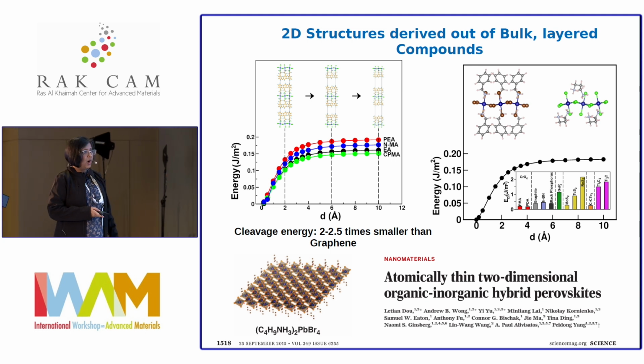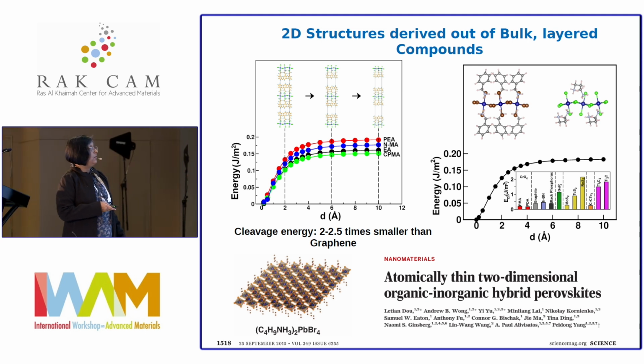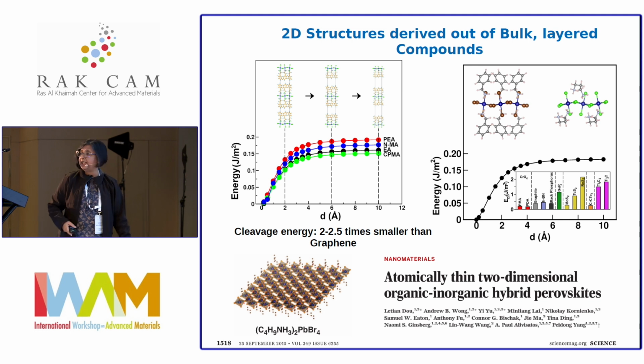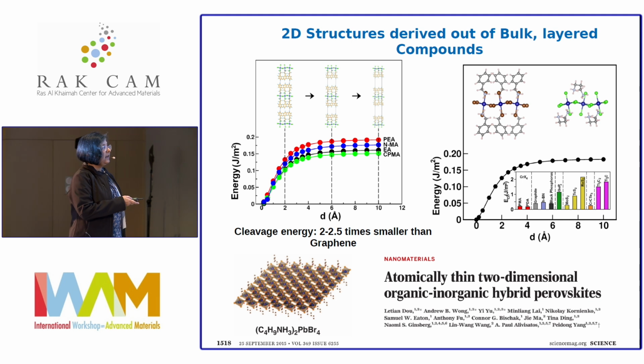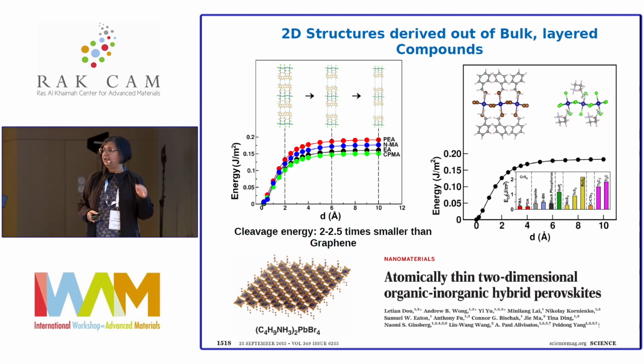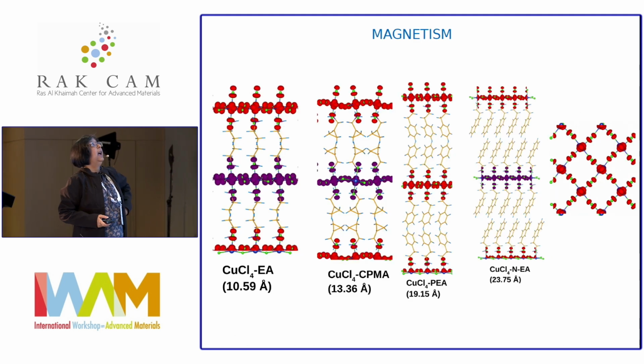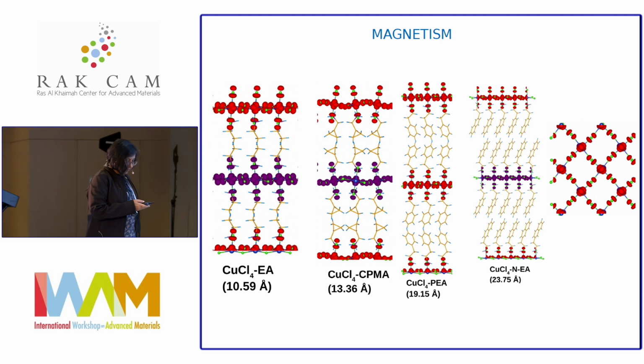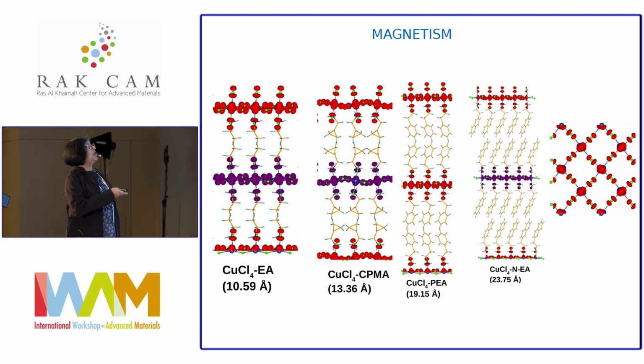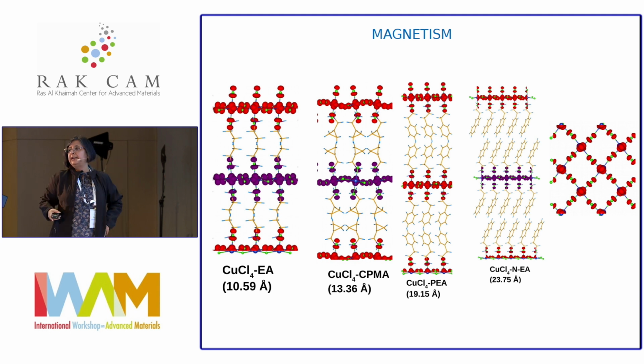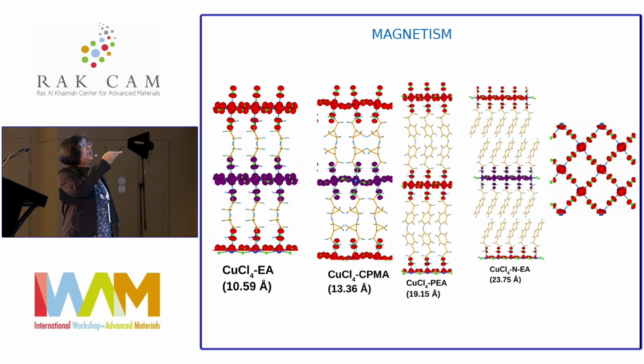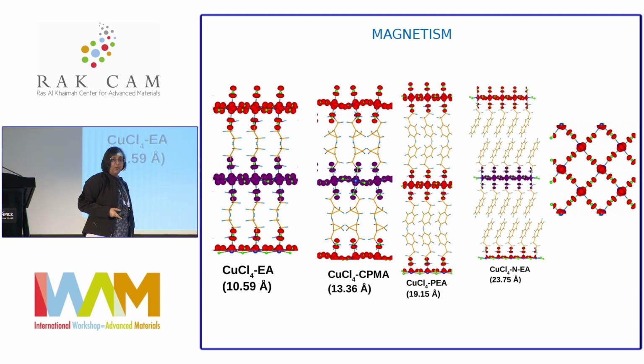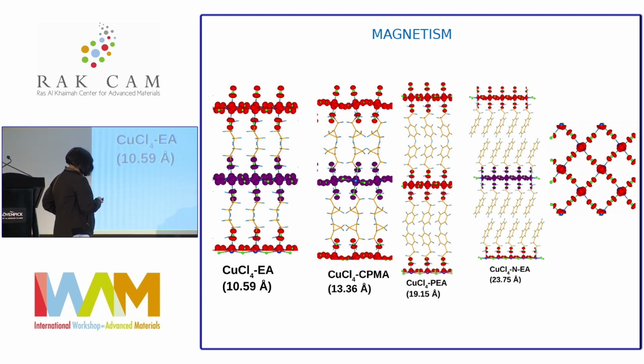And indeed, that is possible, because we then found this paper in Science where they took this material, lead bromide with this organic ligand, with exactly this layer structure, and they could make an atomically thin two-dimensional layered structure of it. So that is possible. Now, what about their magnetism? We found that if you look at the magnetism of the bulk structure, in plane, the copper spins are all ferromagnetically aligned. In between the layers, they are either anti or ferro, but this interlayer magnetic interaction is extremely small because it has to pass through the spacer layer.